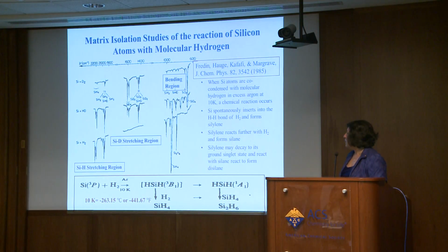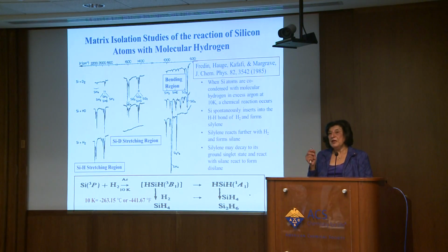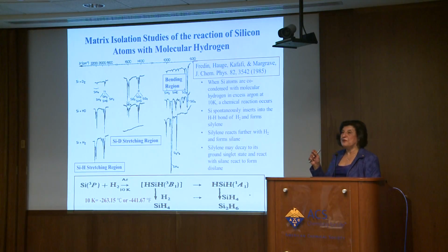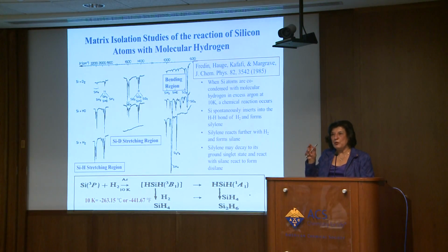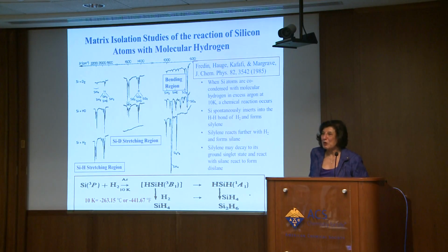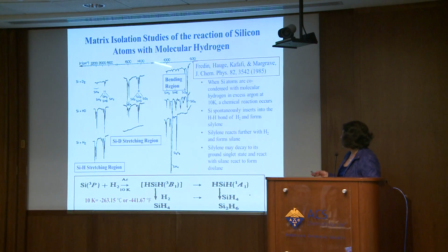One of the fun experiments that we did: we wanted to not only react silicon with D2 or H2, which is molecular hydrogen and deuterium, but also with HD. In this experiment, we had to react molecular hydrogen with molecular deuterium to make HD. This is a very exothermic reaction, so it's really a little explosion. We had to be very careful to introduce a small amount of molecular hydrogen and molecular deuterium to make HD. Every time we turned the valves to introduce these two species, we heard a noise, which was really a small explosion. But anyway, this helped us succeed in determining the identity of these species.